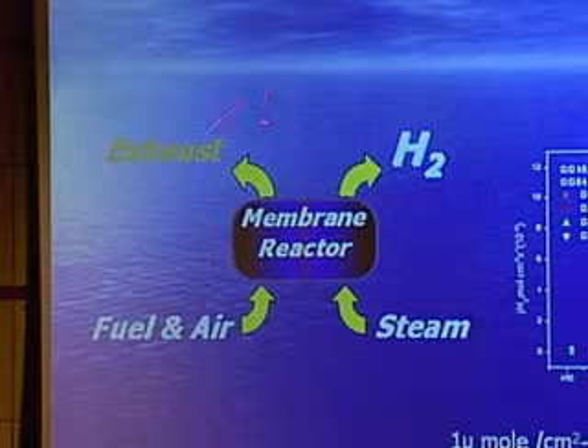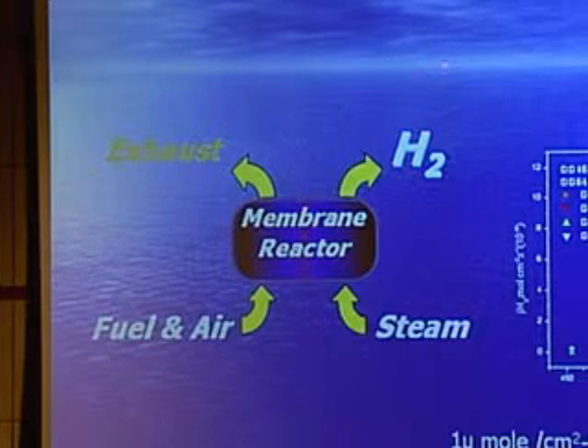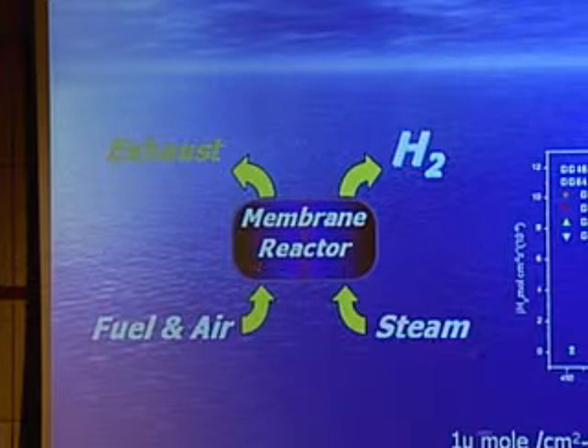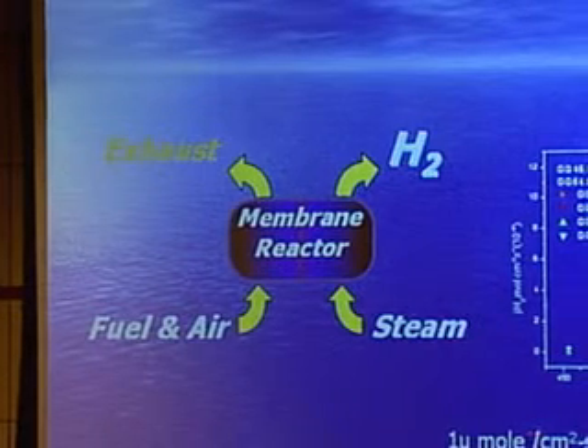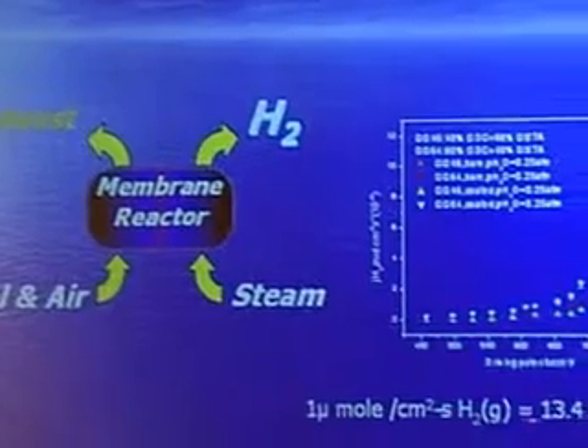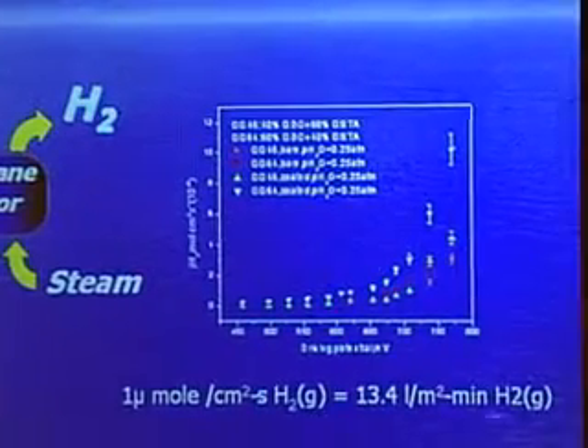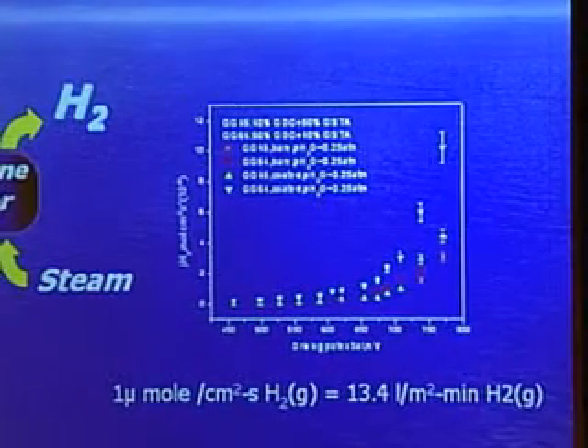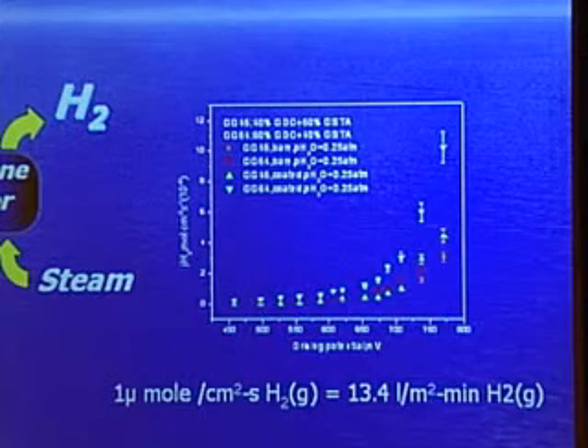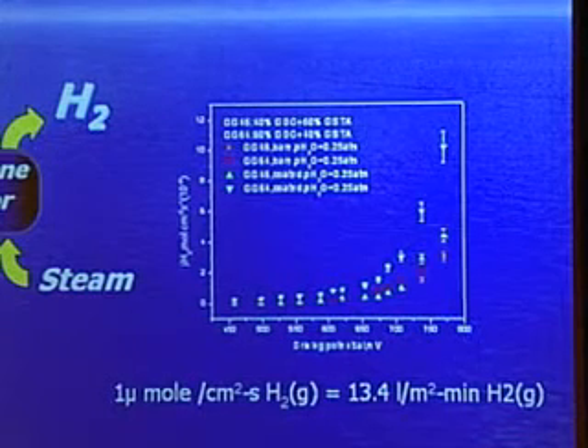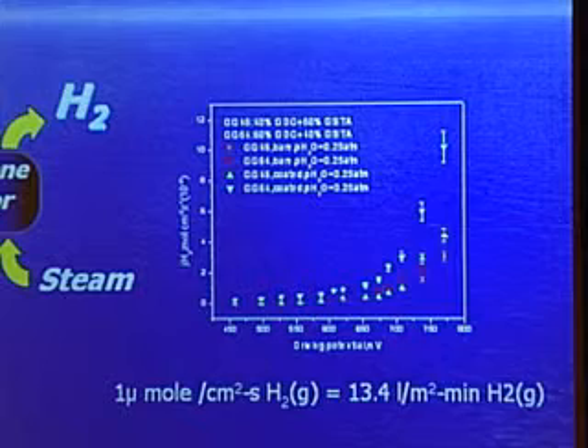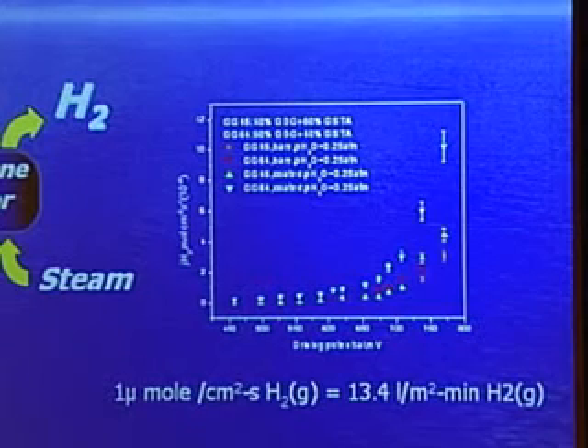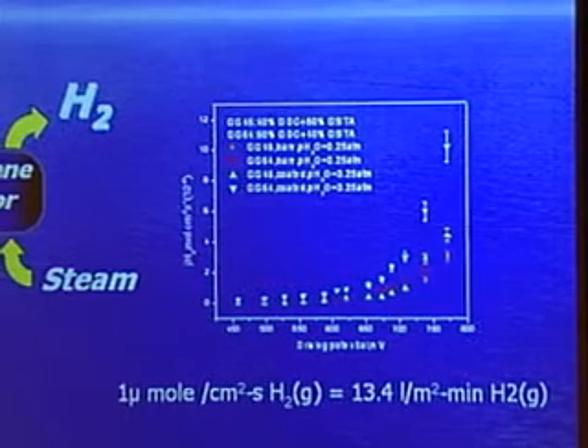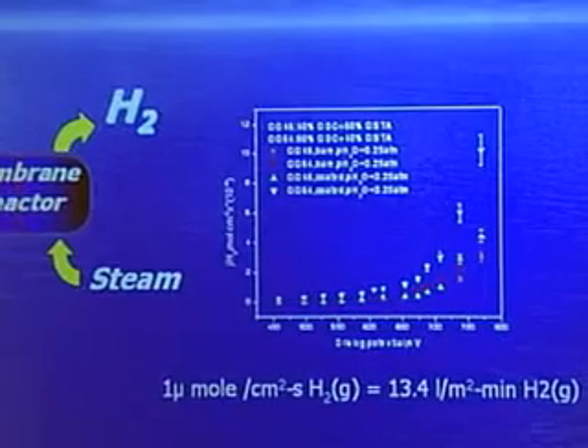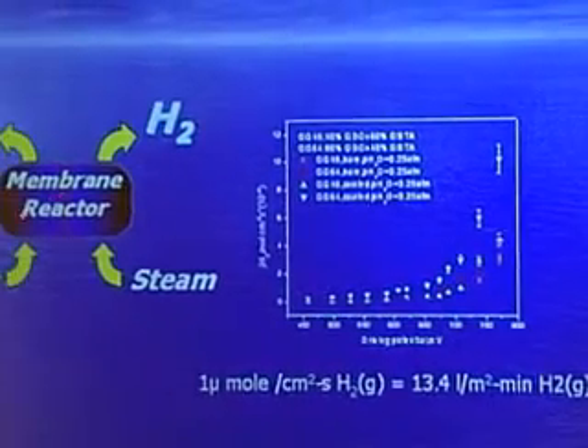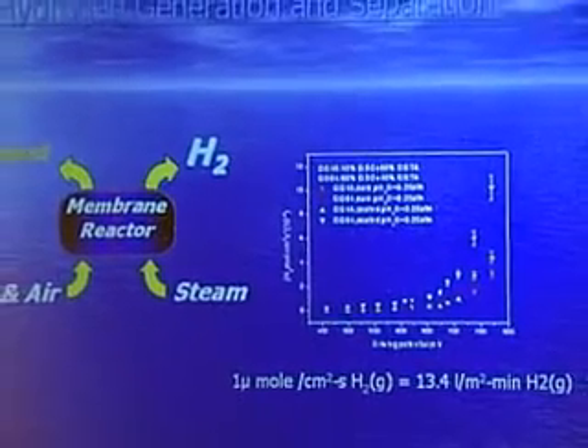We have used these membranes that were developed in our lab, and we have been able to get flux on the order of 13.4 liters per meter square per minute of hydrogen. And this rate is sufficient to power small low temperature fuel cell systems based on polymer electrolyte fuel cells, where having ultra pure hydrogen is the major challenge. And this technology will enable us to do that.